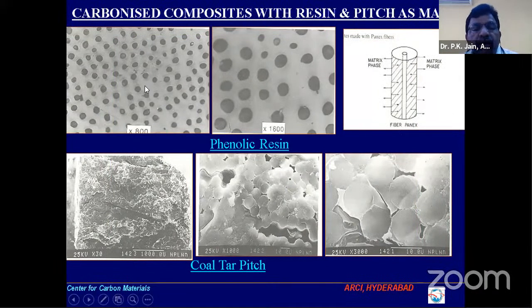The very strange thing we observed was that the fibers were not stabilized, they were so weak, and the interface was so strong that the matrix, during the heating, pulled the fiber, and you will get a hollow. The fiber pull was so strong that it has become a hollow fiber. But you can see the annular fibers, many fibers are there, and there is an annular gap. The concentric gap was there, and the fracture surface, these are the coal tar pitch, the fracture surface was also very catastrophic.